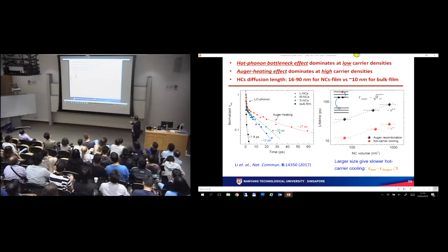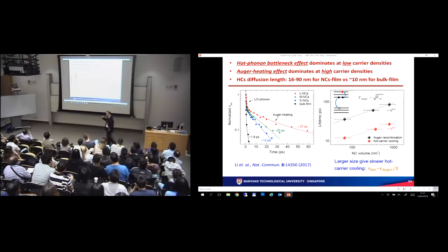But what I want to draw your attention to is, given the lifetimes that we measured, we made an estimate of the diffusion lengths for these hot carrier lifetimes. That gives you about 16 to 90 nanometers. This is a fairly thick film, and it's still possible to make a device with this kind of thickness. If you compare for bulk films, where the lifetimes were only about 0.4 picoseconds, that restricts you to something like less than 10 nanometers, and it's very challenging to even attempt to make a device with a 10 nanometer layer.